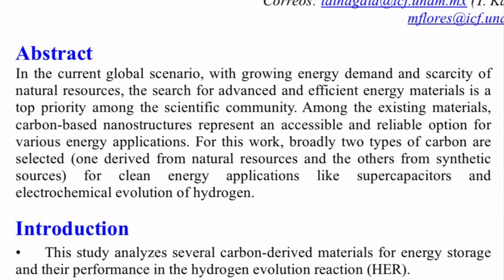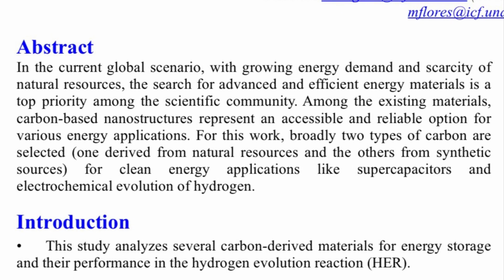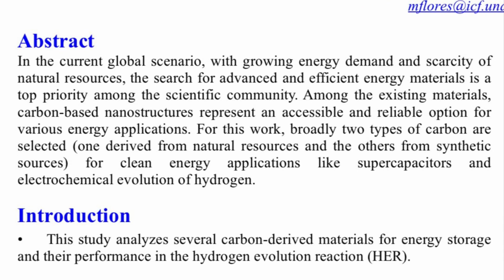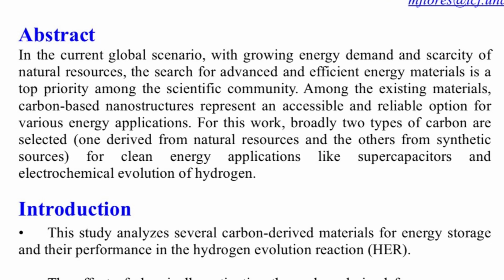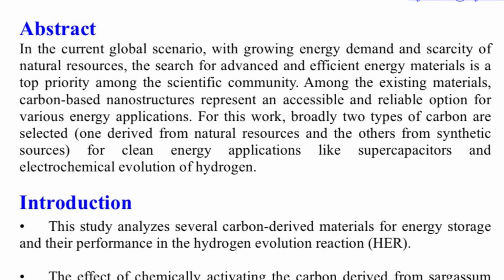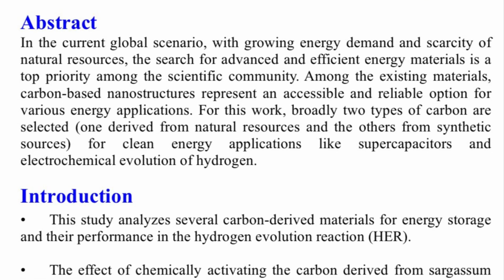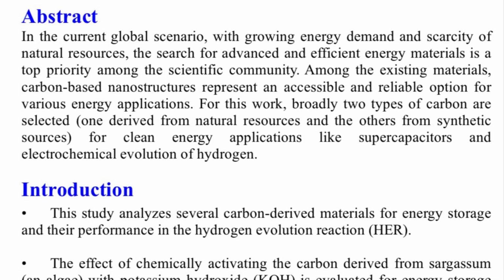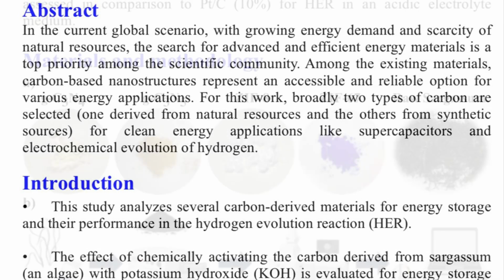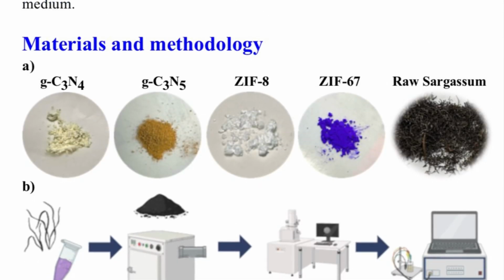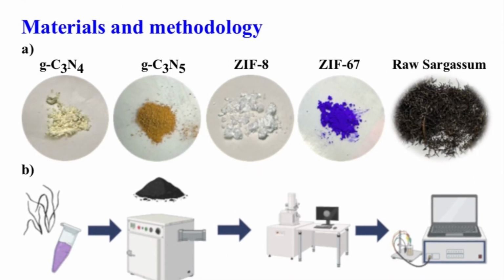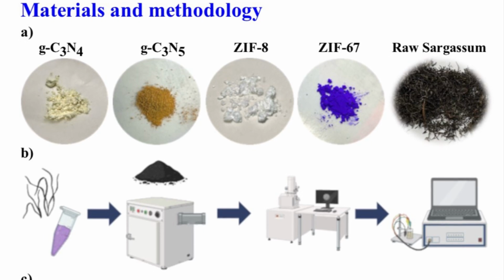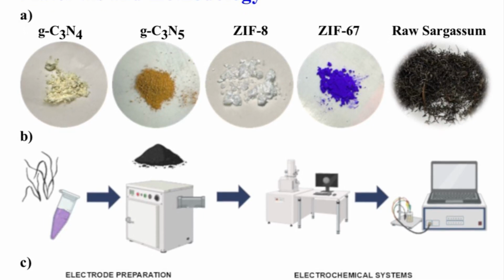For this work, broadly two types of carbon are selected: one derived from natural sources and the other from synthetic sources, for clean energy applications like supercapacitors and electrochemical evolution of hydrogen. For this work, we tested 5 porous materials: 2 graphitic carbon nitrides, 2 metal organic frameworks, and carbonized sargassum.